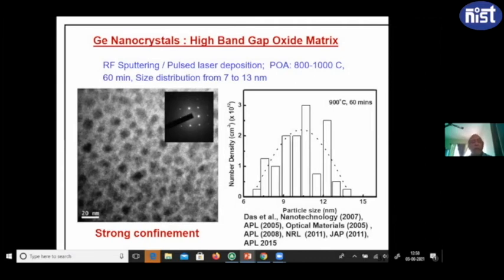But Devashish Panda also worked a lot, Kostov Das, etc., to get light emission from so-called silicon. So what we did in this case, we made germanium nanocrystals, because germanium is also a group four element. So we put germanium nanocrystals, and if you see the TEM here, in a silicon dioxide matrix. And what happens, due to this quantum size effect, the germanium nanocrystals now almost behave like a direct band gap material. Because the difference of energy between the indirect band gap and direct band gap in germanium is very, very small. So if you put some quantum size effect, that means put germanium nanocrystals or quantum dots embedded in a high band gap matrix, they almost behave like a direct band gap material.